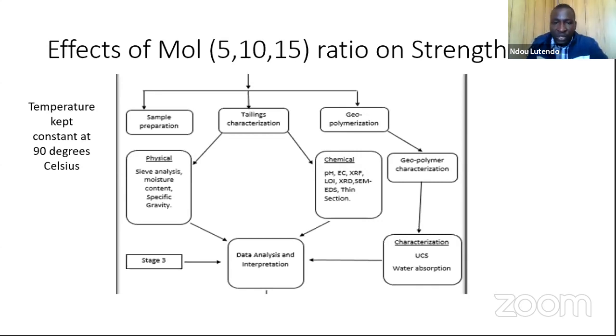To determine the elemental composition of the tailings, I used a method called X-ray fluorescence, which is XRF. XRF is a sensitive method, but it does not account for organic material in a sample. Hence, I did LOI, which is loss on ignition, to determine the amount of organic matter that was lost.